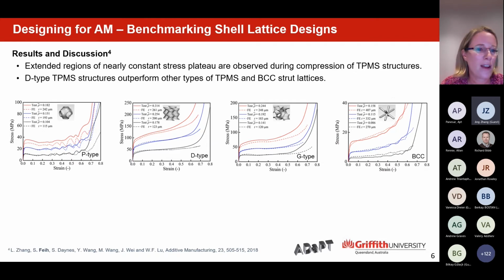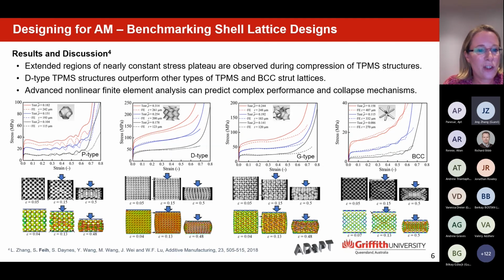So as I said, we're really trying to push the limits of the equipment. And if we do this kind of ranking, you can see it in the paper, then the D-type shell-based structure performs best. Now, why is that the case? And that's where simulation comes in and gives a bit of explanation.